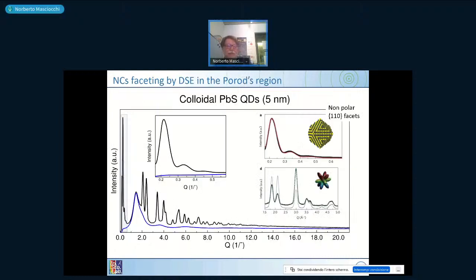So the final refinement looks like a normal Rietveld refinement. You have data and model on top of each other. You don't see a difference because they match very well. On the bottom here in blue, you have the trace of the solvent, which had to be collected separately because the material is suspended in solution. But one thing you can see here, at a very small angle, you have a strong peak with some variations. And if you take the small portion here, you see that these peaks have some kind of periodicity.